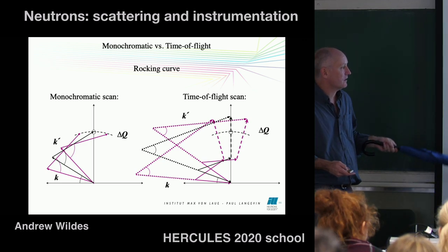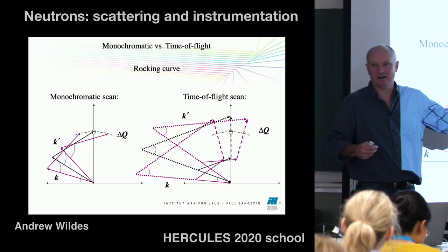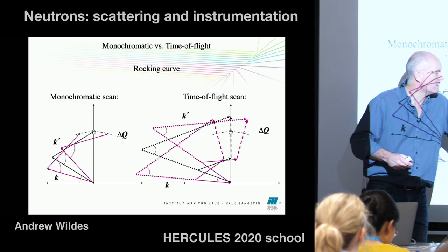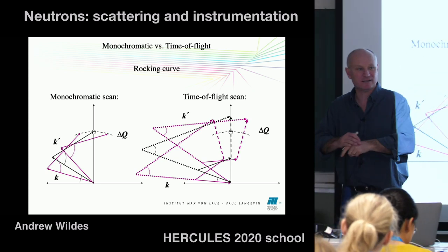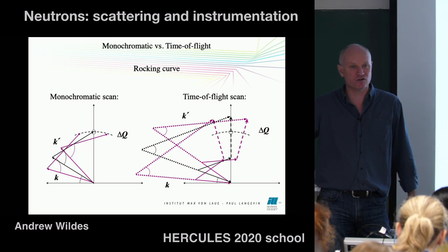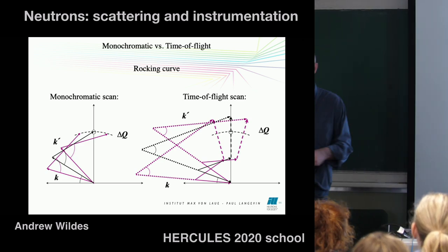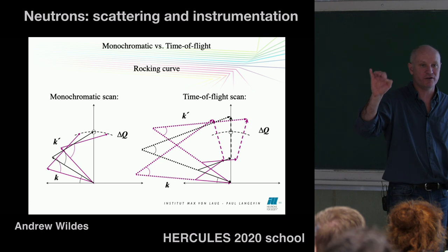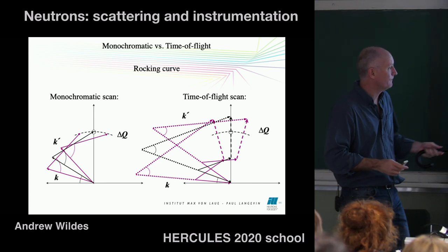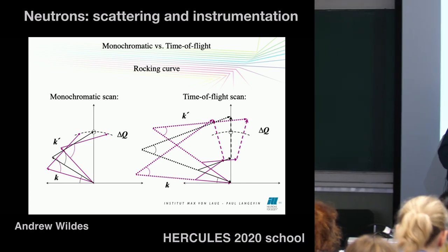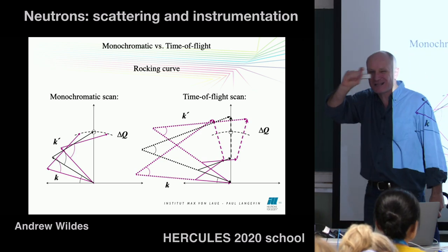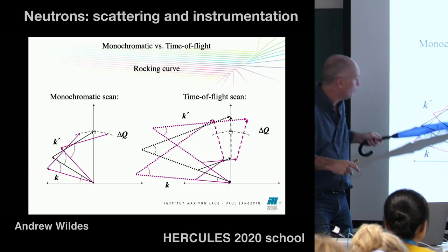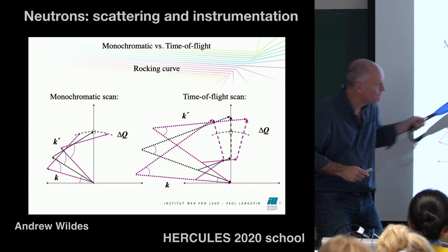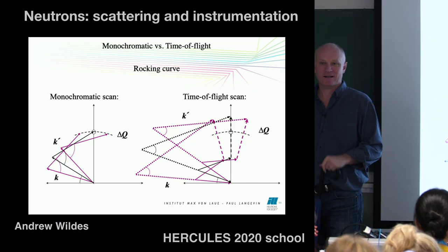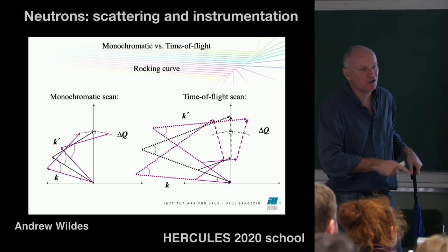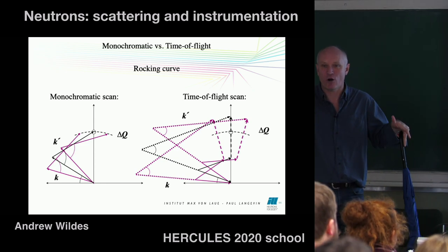The flip side, though, is that these measurements tend to be sort of inefficient. If you're only interested in a very small region of reciprocal space, you're collecting a lot of stuff that you're not necessarily interested in. In a monochromatic scan, you can focus all your intensity at that one position you're interested in. So in terms of speed, you cover a lot more of reciprocal space here. But if you look at the intensity in a particular position in Q, you're probably better off going this way. So in both situations, you'll get the same information. You need to think about which instrument and which technique you want to use to be able to work out the optimal way of doing the measurement.